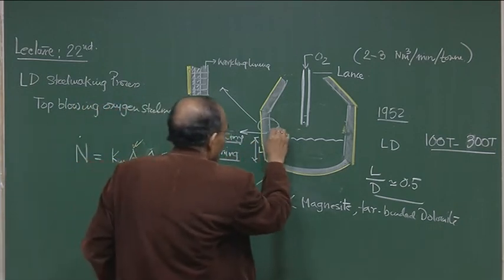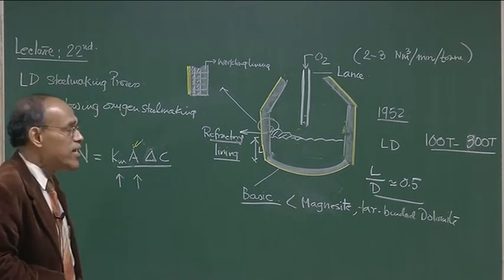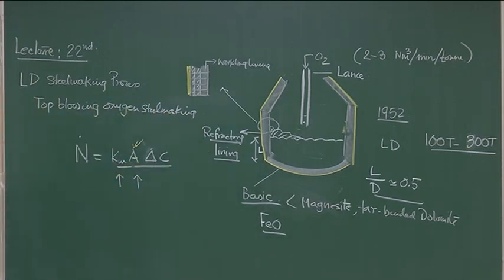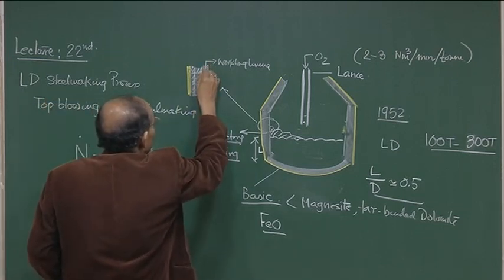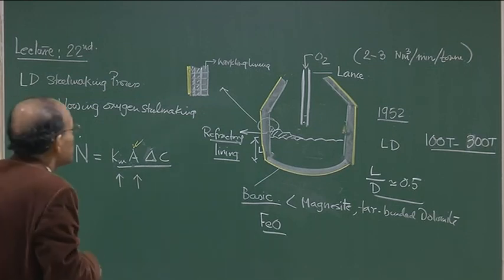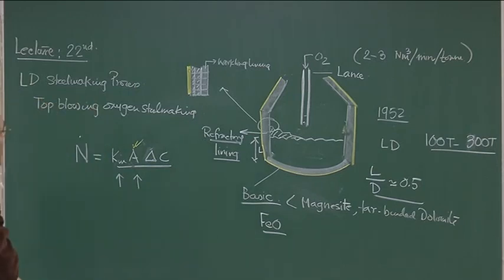For example, in this particular region, the slag may be quite high, okay, and the slag contains FeO, as you all know, and FeO is very corrosive to the basic slags, to magnesite as well as tar bonded dolomite. So we have also here cardboards and glass wool, etc., with which the joints are reinforced, because the bricks are going to expand when they are heated, and these cardboards, asbestos, etc., give adjustment to the thermal expansion and contraction of the